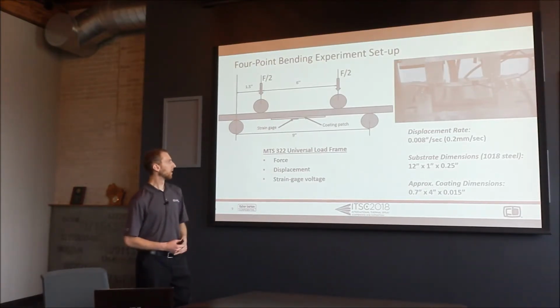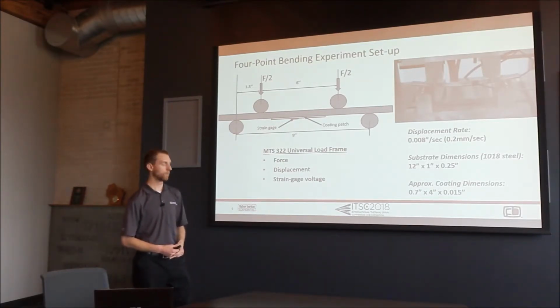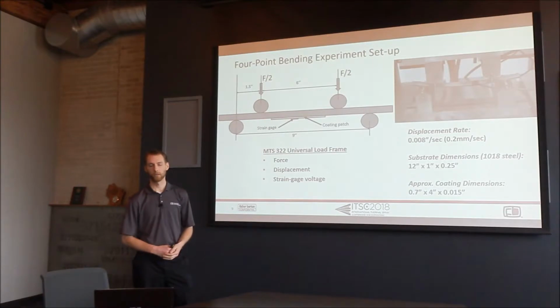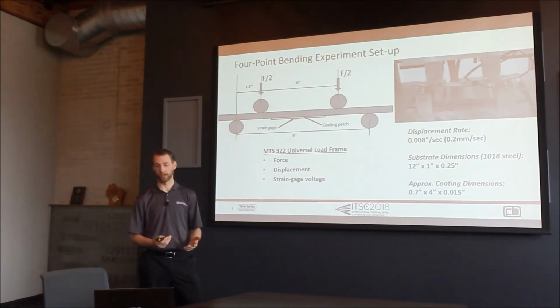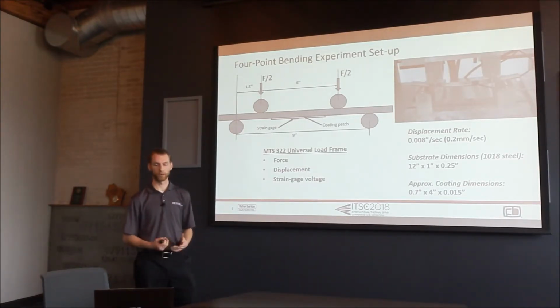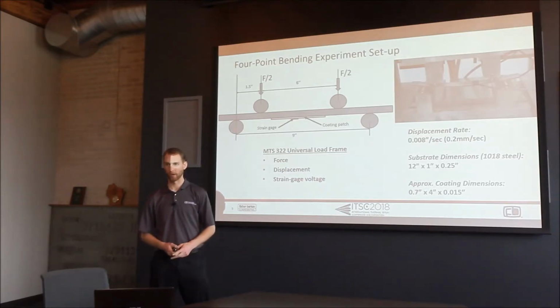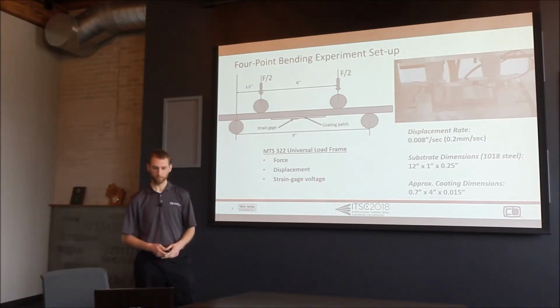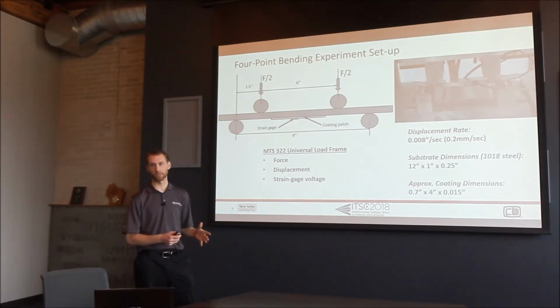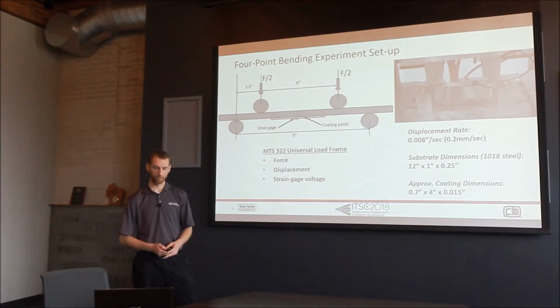So the 4-point bend test is pretty simple fixturing. And then we're using our MTS 322 load frame to measure force and displacement, and then from the strain gauge, look at the voltage data, so we can show the strain at the coating surface. Our coatings are comparable to the ASTM C633 approach at about 15 thousandths thick.